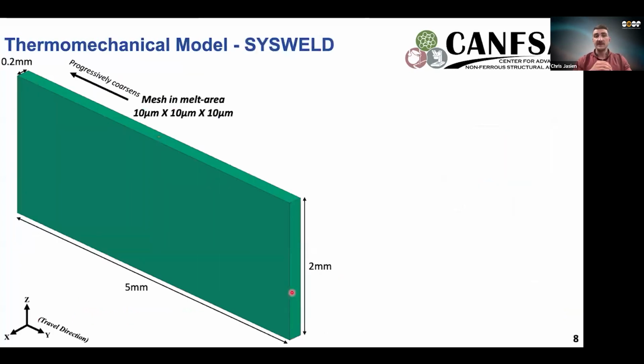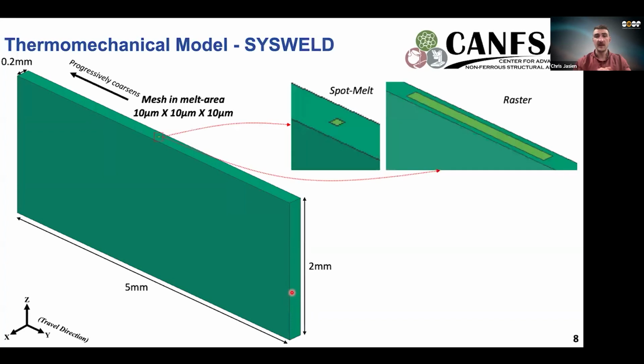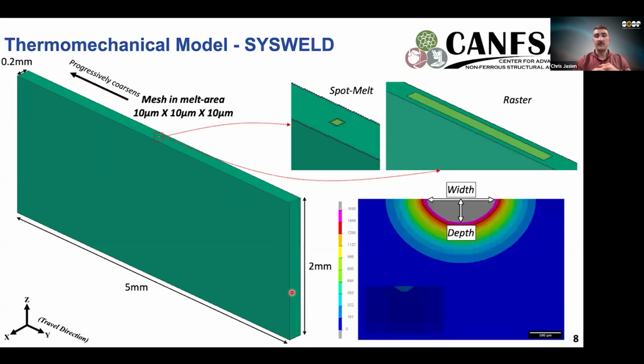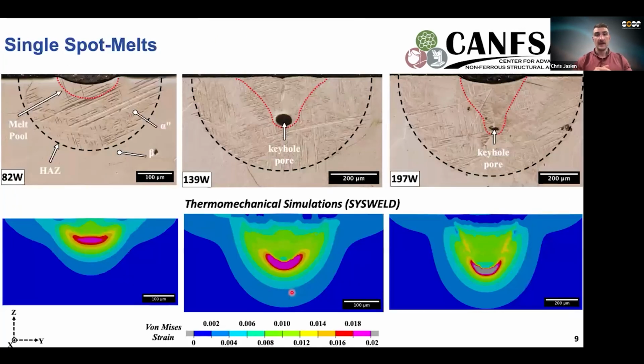So we used a thermomechanical model called SysWeld, and the sample geometry is outlined and shown here for both spot melt and raster conditions. And I'll talk about the rasters when we get there. And then we used our information from our experiments, which got us a width and depth of these melt pools, to calibrate our models to be accurate in that sense.